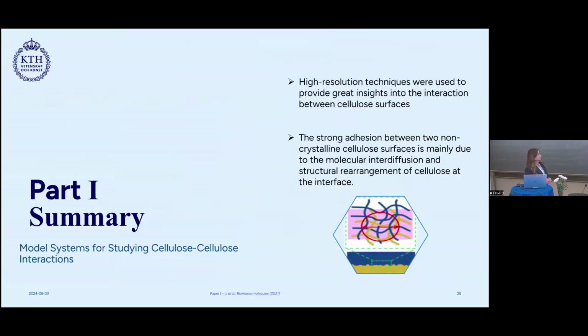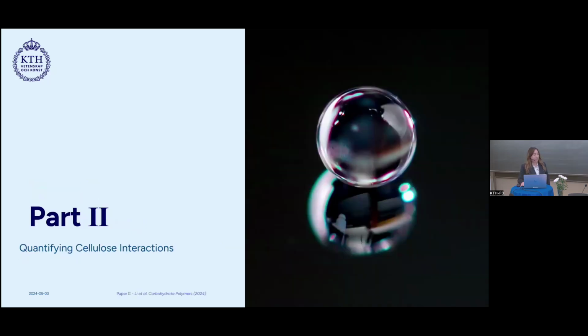So as a summary for part one, high-resolution techniques were used to provide great insights into the interaction between cellulose surfaces, and the strong adhesion between two non-crystalline cellulose surfaces is mainly due to the molecular interdiffusion and structural rearrangements of cellulose at the interface. Now on to part two.